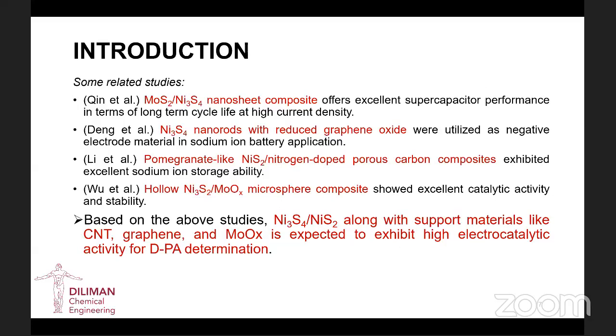So other related studies include the synthesis of molybdenum sulfide and polydymite nanosheet composite for supercapacitor performance, which offered long-term cycle life at high current density. And then nickel polydymite nanorods with reduced graphene oxide as negative electrode material in sodium ion battery application. And then the combination of nickel disulfide with nitrogen doped porous carbon for supercapacitor. And this is for sodium ion storage. And then we have polydymite and molybdenum oxide composite showing excellent catalytic activity and stability in a study by Wu et al.